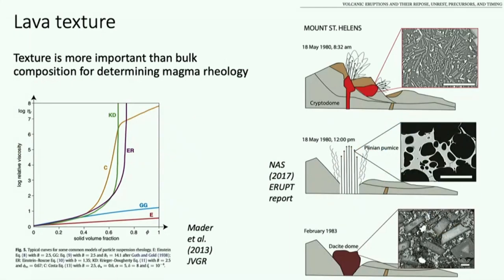And in fact, crystallization is really important, right? So the texture of lava is more important than its composition in determining magma viscosity. So a kind of summary diagram here is relative viscosity. This is the viscosity of a suspension relative to the viscosity of just the liquid. So this could be oil with sand in it, or magma, lava that is molten silicate with crystals in it, whatever you want. So if you have 60% crystals or 60% sand, then you're looking at probably about a factor of 1,000 increase in the viscosity. Our current favorite model on here, by the way, is the one labeled C, but this is another thing that we argue about, is what's the right thing to use?